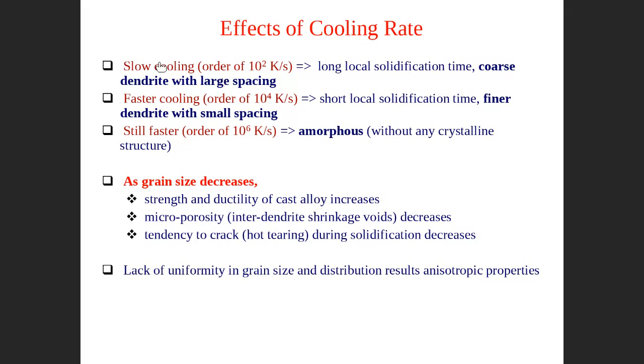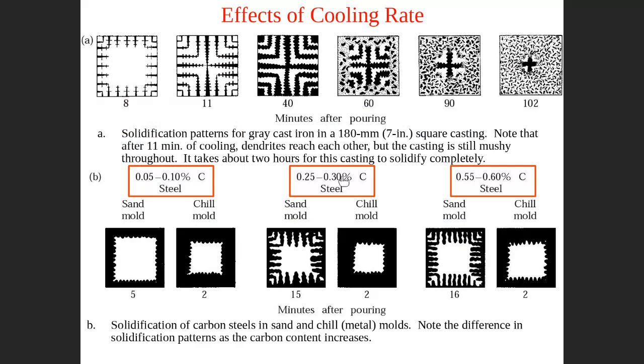So whenever you have a higher cooling rate, you get a smaller grain size. When you get a smaller grain size, the material has higher strength and also becomes more ductile. Microporosity will also decrease. The tendency to create cracks during solidification also decreases. This is the effect of the cooling rate.